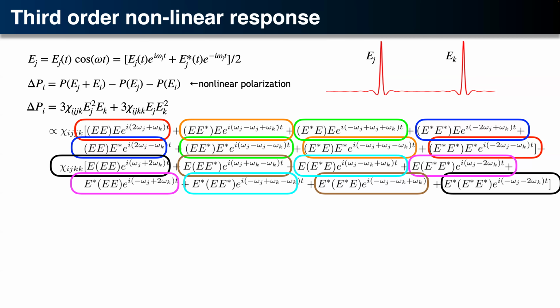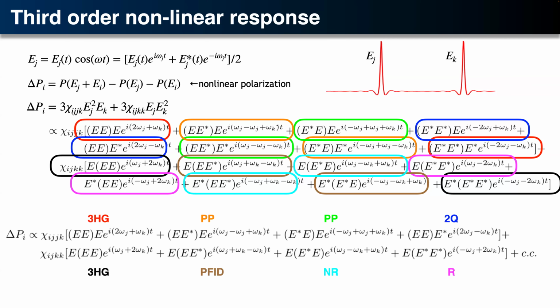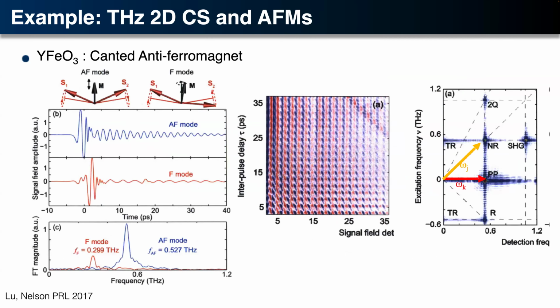There are different processes. But one of the reasons that we are plotting things in the 2-dimensional plane is this: these are experiments done on a canted antiferromagnet, yttrium ferrite. And that's what data looks like in the time domain. When we take the Fourier transforms, we have these different peaks that appear in different places in the 2D plot. And one of the features of nonlinear response: in linear response, if I have a ground state and an excited state, there's really just one way to excite from the ground state to the excited state.